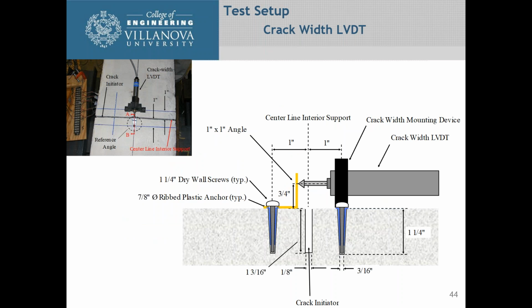Now, we knew that we were going to get cracking at the center line, at the point of maximum negative moment. And we wanted to be able to measure that crack. Now, one way you could do it is, once the beam cracks at that location, stop the testing and then install this type of apparatus. But what we did is we actually saw cut across the beam at about 3/4 of an inch deep by 1/8 inch wide, what we call the crack initiator. So by putting in a sawed cut joint there, we guaranteed that when the cracking first started, that's where it was going to be cracking.